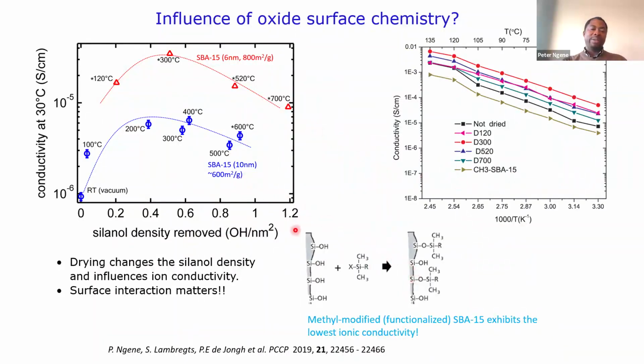And what we can even do is completely modify the surface groups. We can remove the silanol by doing what we call methyl modification, silanization, and we remove all the surface groups, and we can even have a very hydrophobic silica surface. When we did that, you can see that we go from this high conductivity, the highest here, to very, very low conductivity here.